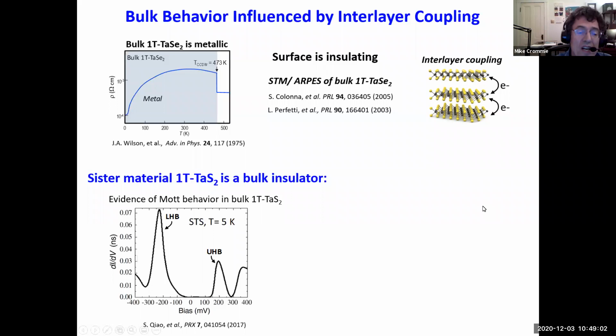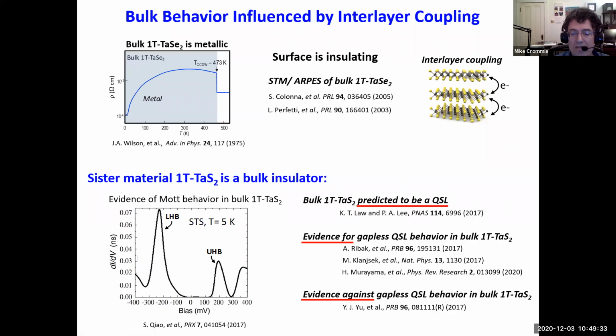There's another material, the sister material 1T TaS2, where you replace the selenium with sulfur. And this material is even more famous than TaSe2 because in bulk it is an insulator. You can see evidence for that here. This is STM spectroscopy done by, I think, Yayu Wang's group a while ago. You can see the nice lower Hubbard band and upper Hubbard band and a nice energy gap. So this material is an insulator, and most people believe it's a Mott insulator, although even that is controversial.